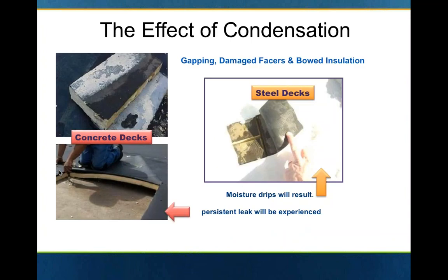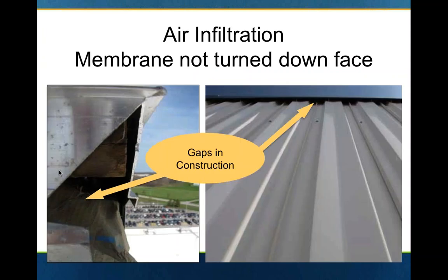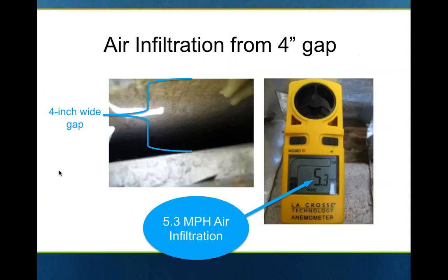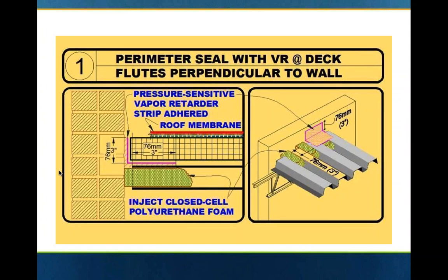What can happen is moisture entering the roofing assembly can cause bowing and warping of and damage to insulation facers. And particularly on white membranes in cooler climates, that moisture can hit its dew point and condensate on the underside of that white membrane. So it can create some serious issues. Simple gaps in construction can move an awful lot of moist air. A 4-inch gap is moving air at 5.3 miles per hour. And so we want to seal angle changes and around penetrations.